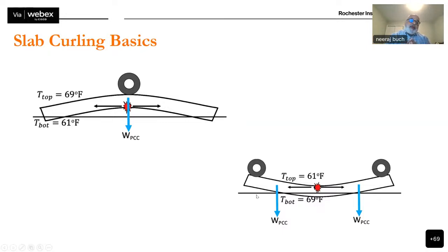So if you were to do a falling weight deflectometer test on a joint when the slab is positively curled, you will get artificially lower deflections. Versus if you were to do it when the slab is negatively curled, you will get artificially higher deflections. That doesn't mean that the joint is good or bad. The deflections are a result of the geometric deformation of the concrete slab, which could be either positively curled or negatively curled as a function of the temperature gradient across the thickness of the slab. This is a very fundamental concept that anyone in the business of concrete pavements should be aware of, especially when you are measuring deflections.